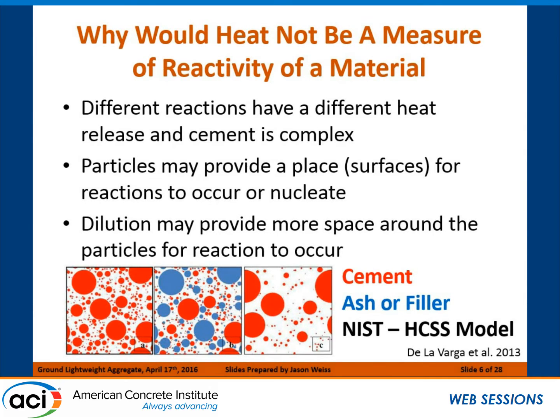Here you can see some work that was done with Igor and Dale Bentz, where we used the NIST hard core soft shell model. The basic idea is that this is pure cement, and you see all the little red balls representing the different size particles of cement. When you start replacing 40% of the system with an ash or a filler, you see the same particles appearing there because we've matched the particle size distribution, but now they're going to react at very different rates, and that's going to have a very different impact on the overall performance.